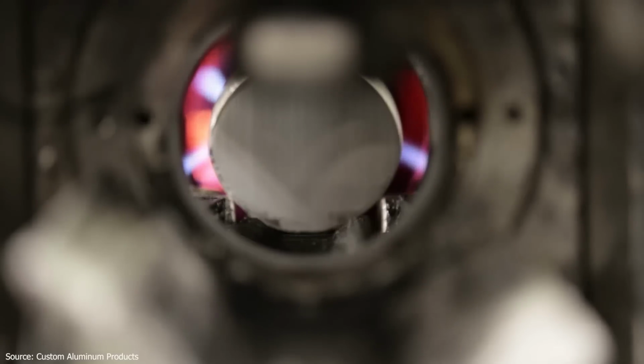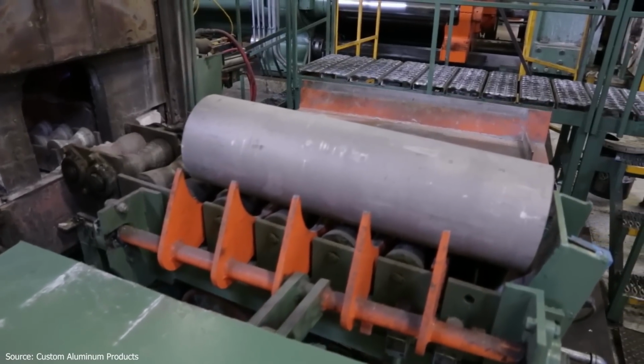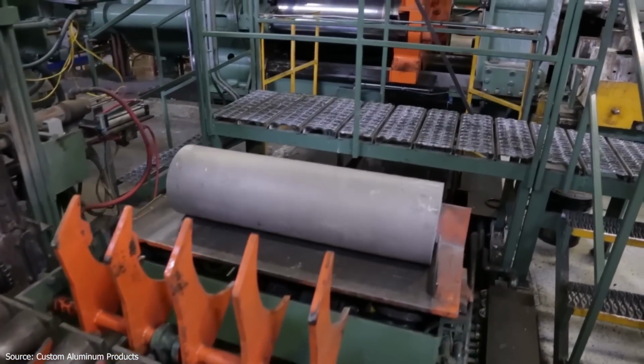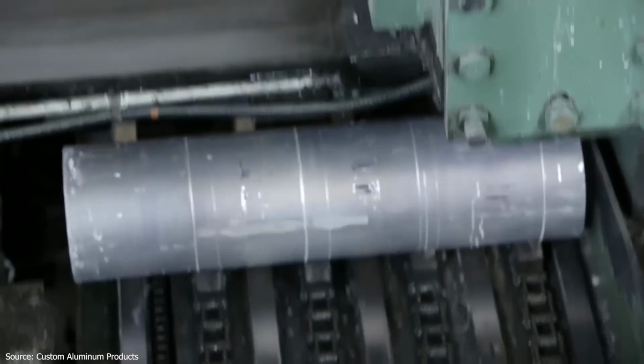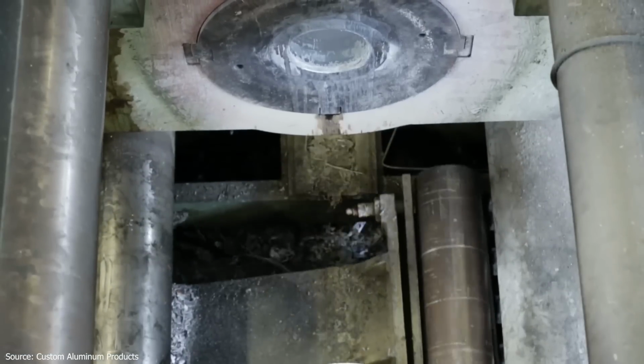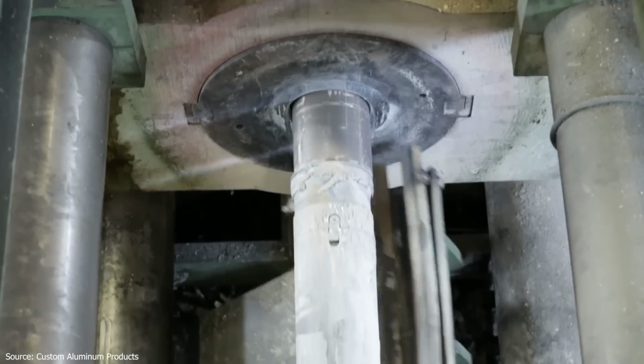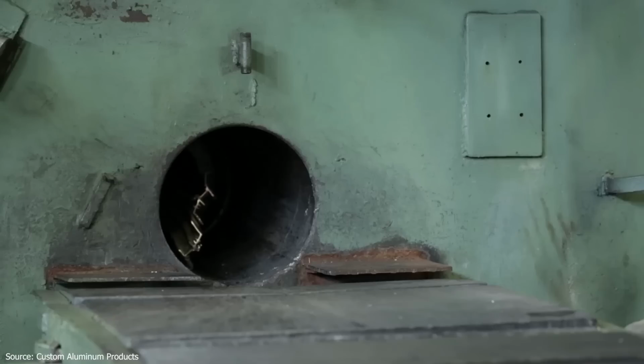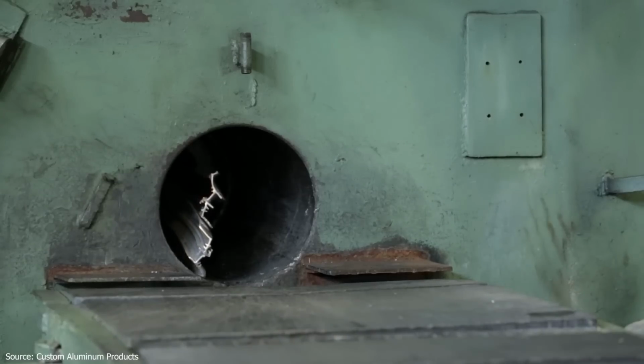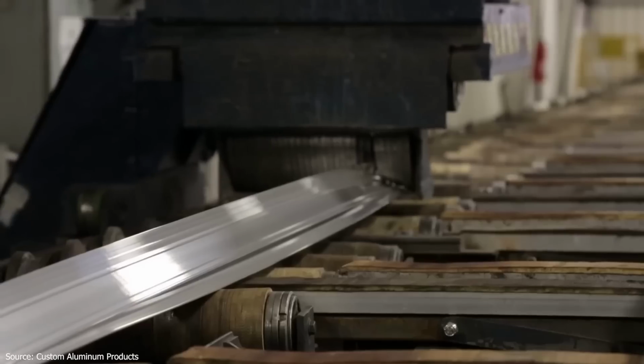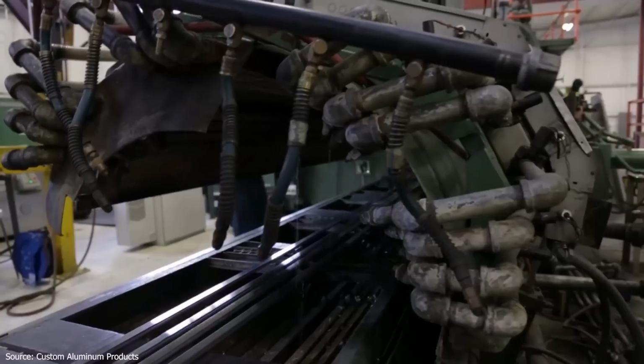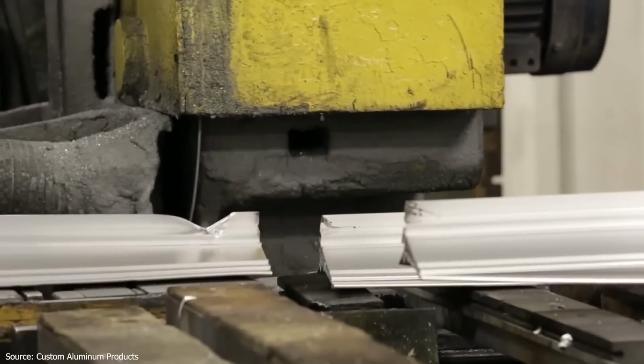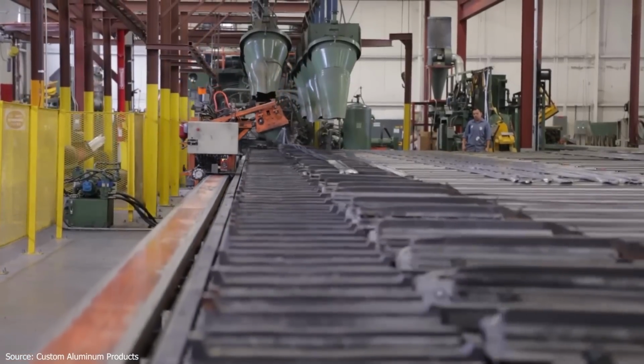The extrusion process begins with 22-foot-long aluminum logs weighing around 12,200 pounds, commonly in 7 inches, 8 inches, or 10 inches diameters, using alloys like 6063, 6061, 6463, and 6005. Heated to 900 degrees Fahrenheit, the log is sheared to a 30-inch billet and pressed with up to 3,000 tons of force through an H13 steel die, some up to 15 inches in diameter, with 1 to 8 profile holes. The extruded aluminum is cooled by fans or water quenching, stretched 3% to correct distortions, then cut into 20-foot lengths and aged to achieve T5 or T6 temper. Over 12,000 custom profiles have been produced to date.